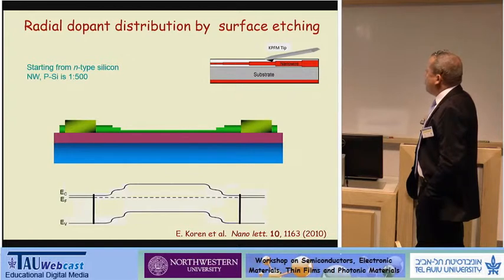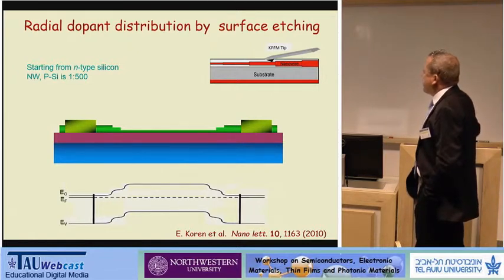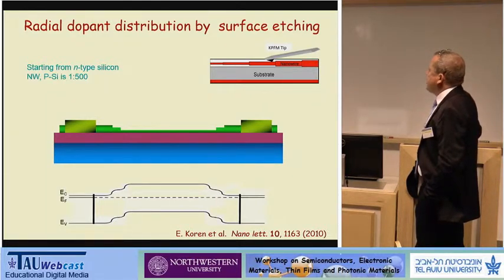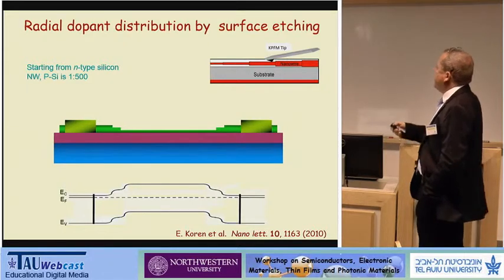And if there are more dopants inside the nanowire, if there are more dopants outside, on the circumference on the surface of the nanowire, and less dopants inside, when you form this staircase structure, the Fermi level and the conduction band minimum will look like this, where you have more dopants on the circumference and less dopants inside.